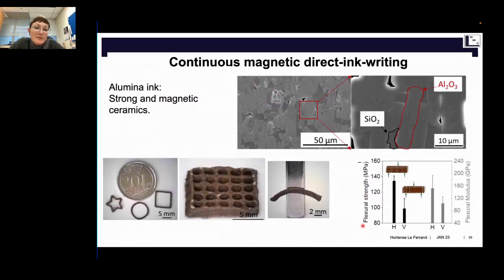The first one is with ink containing aluminum oxide platelets, where we can make strong and magnetic ceramics. So we print and then we sinter at a high temperature. We can make small objects, as you can appreciate on this image. We can make porous objects as well. These objects are usually magnetic because we have to add a lot of iron oxide in our ink. So they will stick to a magnet, and the mechanical properties are anisotropic and fairly reasonable for a ceramic. So yeah, rather high strength and high flexural.